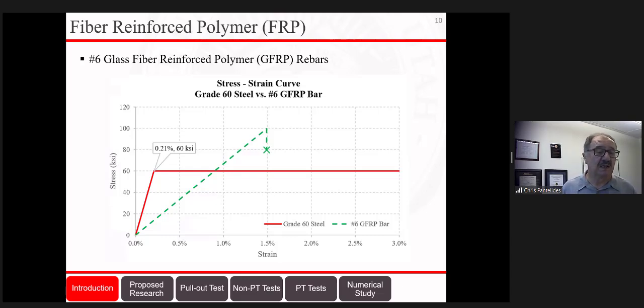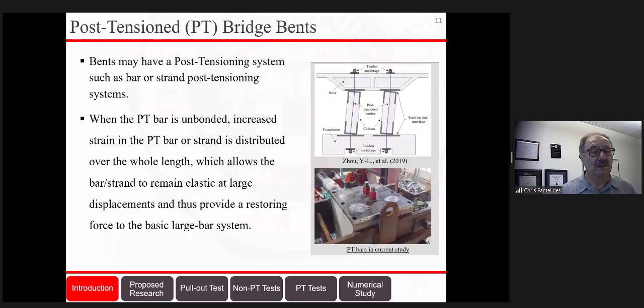Whereas fiberglass has a low modulus, but on the other hand, it has a higher strength of about 100 KSI, as I said. So we tried to combine these two materials to make a good connection. The first two tests, as I mentioned, were not post-tensioned, but the last two were post-tensioned. Here you can see on the right a picture of a post-tensioning system. In this case, we used high-strength threaded bars. Other people have also used strands.